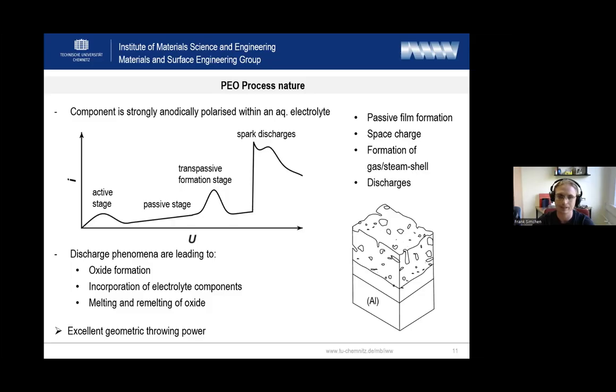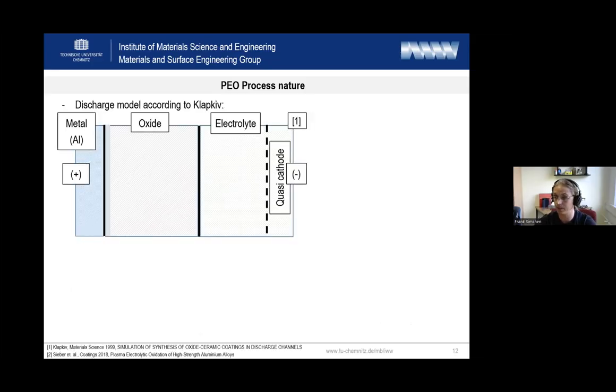So, the method is called plasma electrolytic oxidation because the discharges are indeed of plasmatic nature. The core of every plasma electrolytic discharge is hotter than the surface of our sun. And this causes a lot of interesting mechanisms, which I cannot explain because I'm just an engineer, but they also lead to an interesting aspect, which I want to explain on this slide, based on the discharge model of Klapkiv. So we see here our metal anode, our already formed oxide, our electrolyte, and here close to the substrate electrolyte interface, the quasi-cathode.